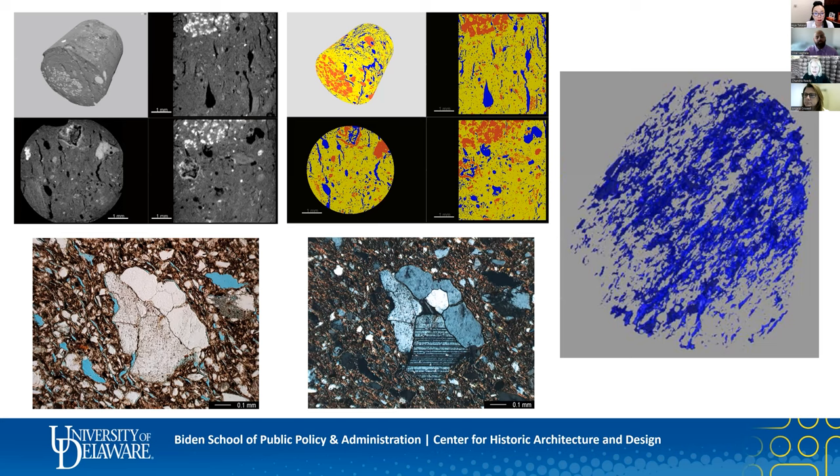There'll be a variety of impurities in the clay, and maybe a complex additive that has a lot of different minerals, or maybe a couple of different additives mixed together. So you might find various feldspars, micas, iron oxide materials, and other things. And so sometimes between the clay and the additive, you can get as many as 12 or 15 different phases, but then additional phases can form during firing. For example, at high enough temperatures, quartz will transform to cristobalite, and then eventually silica glass, and feldspars to mullite. So these phase transformations can help in hypothesizing possible firing temperatures.